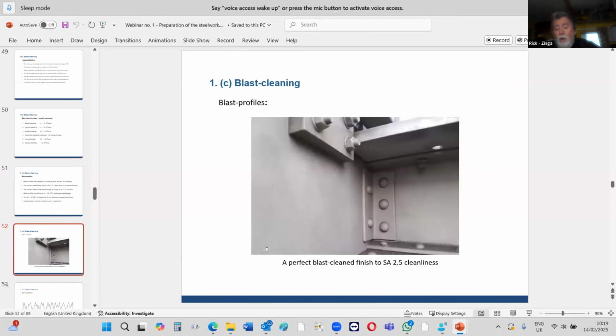And this is an example of a perfect blast. That's a 2.5 cleanliness. So you are allowed a little bit of staining and so on. But for Zinga, the cleanliness is always important as usual, but the depth is the critical factor here. Because even if it's slightly grainy looking, if you've got the depth, the zinc is going to get in there and grip, and it gets harder and harder every week for the first year.